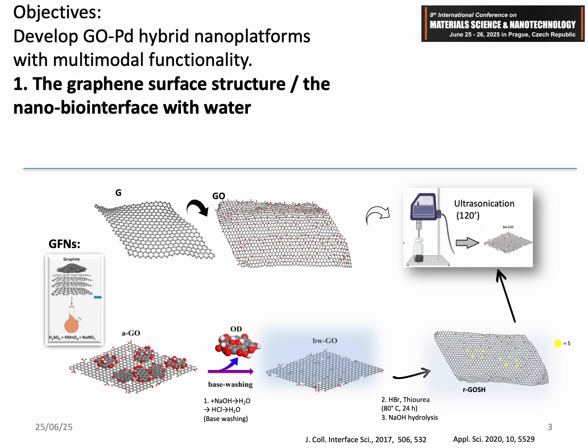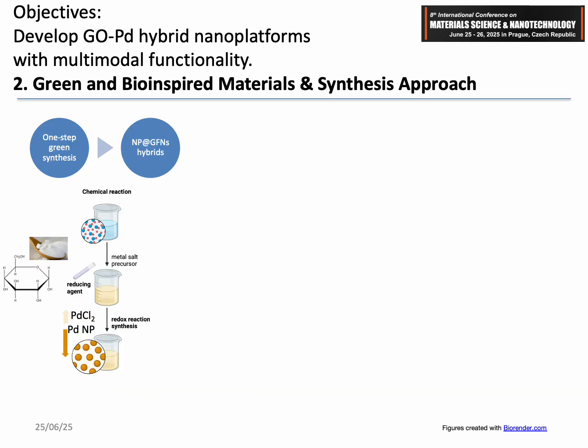Then we did the base washing treatments to obtain the hydrophilic base-washed GO, which is further functionalized by treatment with thiourea and hydrobromic acid at high temperature to obtain the RGO-SH, reduced thiolated GO, introducing thiol groups and restoring the partial conductivity through reduction. Since this becomes again hydrophobic like the graphene, we need to improve the dispersibility and complete the cycle with 2 hours of ultrasonication, which helps to resuspend the nanosheets in solution and maintain a stable dispersion.